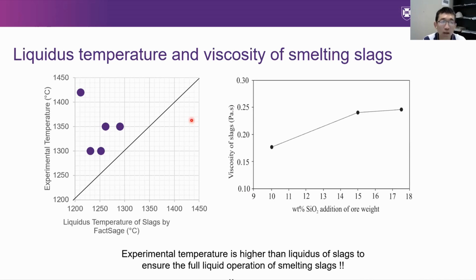So here we compare our experimental temperature and the calculated liquidus temperature of the slag. There is still some room to further reduce the experimental temperature. And then with the addition of the flux, we examine how silica influences the viscosity of the slag. So we calculate the viscosity. It's just below 0.22 Pascal second. Then this is a safe slag viscosity for the operation.